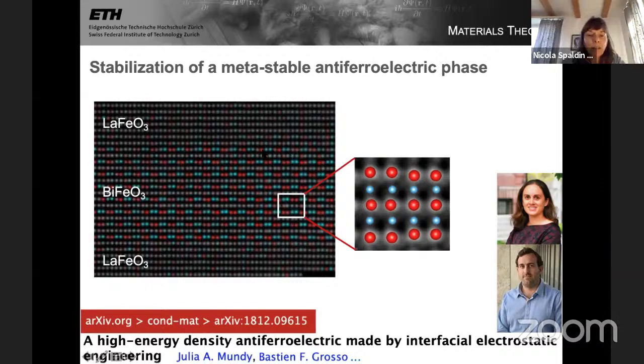And the micrograph has been artificially colored such that the blue color is showing bismuth atoms that have shifted upwards relative to the average, and the red color is showing bismuth atoms that have shifted downwards. So normally, if this were the usual ferroelectric ground state of bismuth ferrite, all the bismuths would have gone in the same direction, right? That would have given it the electric dipole. But here they're going up and down in pairs. And here's a blow up of this section here. We see that 2 of the bismuths have gone up and 2 of the bismuths have gone down.